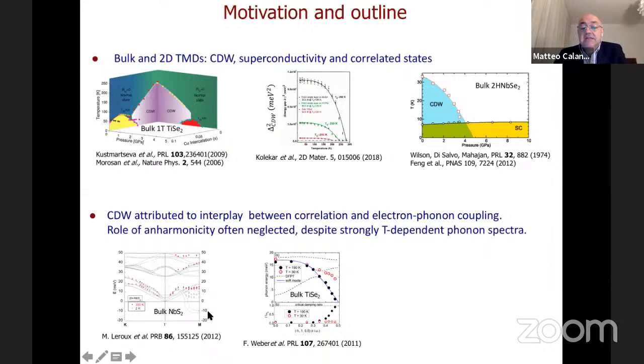On the contrary, the harmonic approximation finds imaginary phonon spectra in the system, so the occurrence of charge density wave instability, while there is none in reality. The same situation occurs in bulk titanium diselenide, where the phonon spectra in experiment are strongly dependent on temperature. So this is a typical fingerprint of anharmonicity. That means that there is something suspicious going on, and that maybe the role of anharmonicity should be considered more in order to study this system.